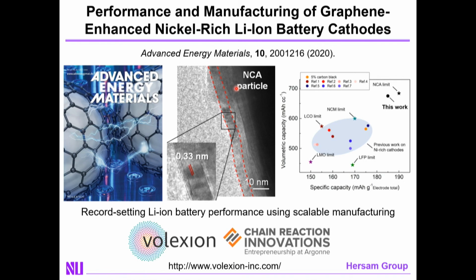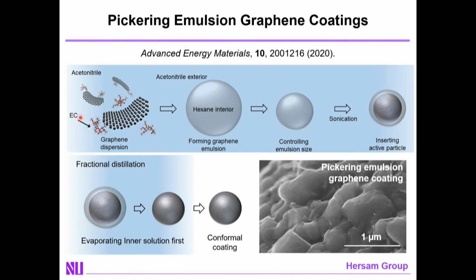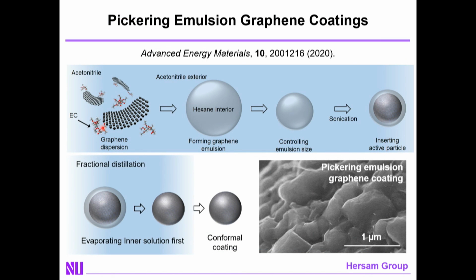Well, one of the subtle details here is that we use a stabilizing polymer called ethyl cellulose, which will give us a secondary polymer coating around the graphene sheets. Now that polymer is not conductive, but what we do is we thermally heat it to about 250 C. That largely volatilizes the ethyl cellulose. Most of it leaves, but a small amount of amorphous carbon remains. That amorphous carbon is templated by the graphene to give you high sp2 content. So you get a secondary sp2-rich coating around the graphene.